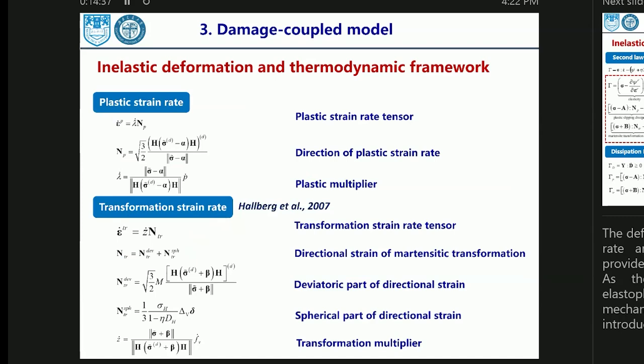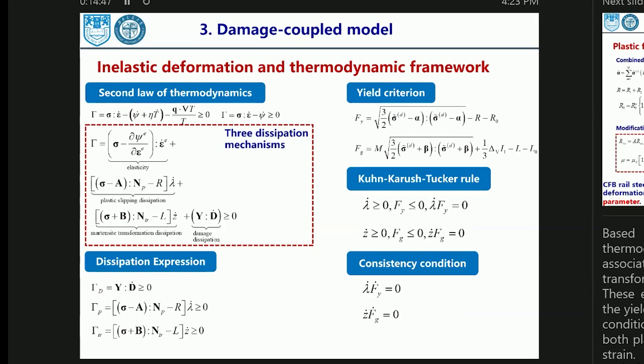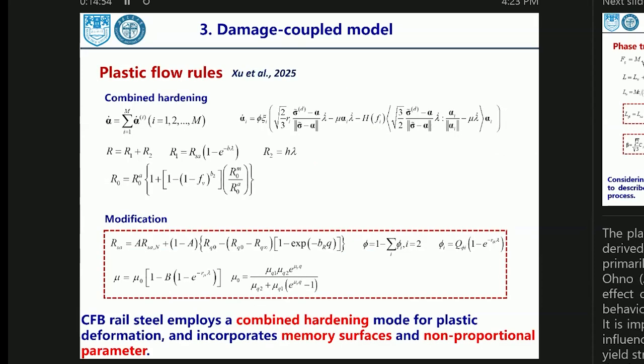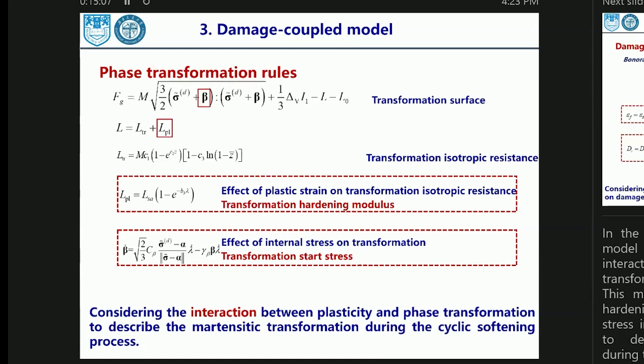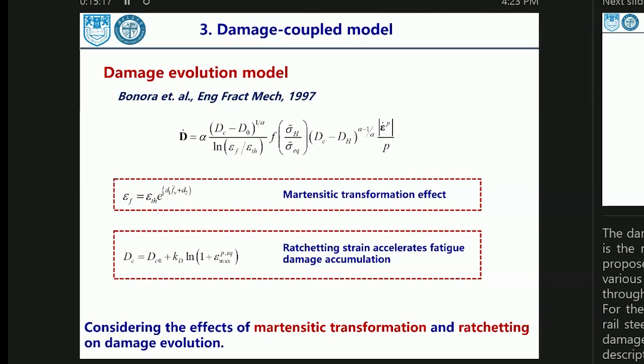And the plastic strain rate and the transformation strain rate are used here. We have two inelastic mechanisms and three dissipation mechanisms, and I will go through them quickly. The plastic flow rule is based on our previous work for cyclically softening materials. For the phase transformation rule, we introduce two terms to consider the transformation and plastic interaction. And for the damage evolution, we introduce the martensitic transformation effect and the ratcheting strain effect.